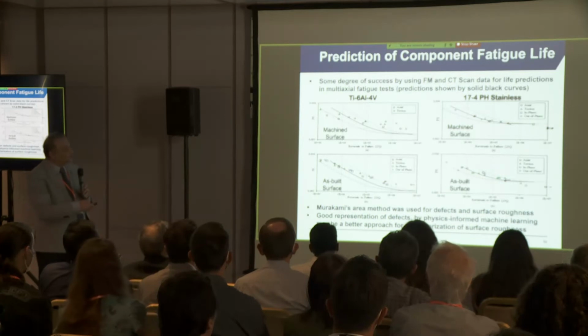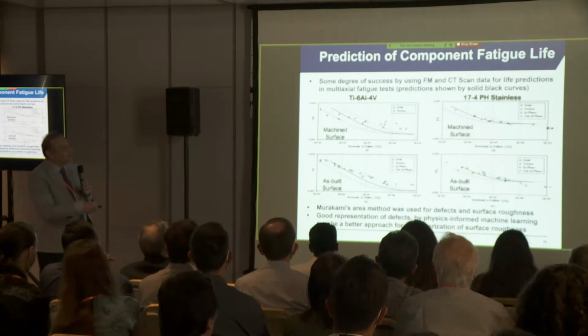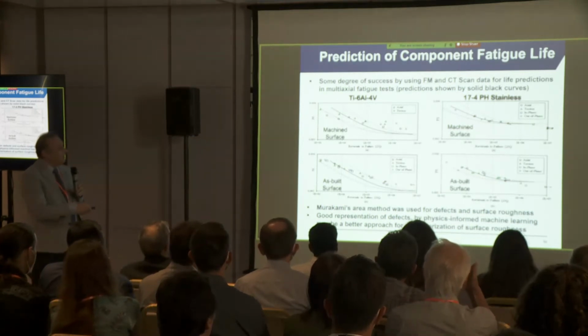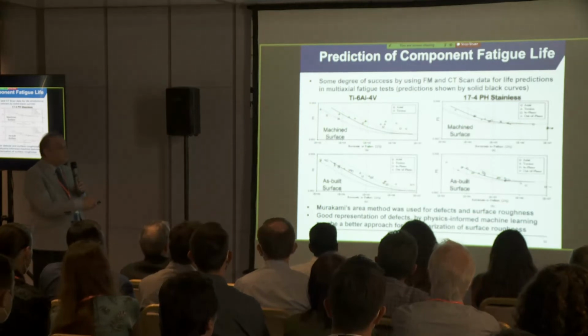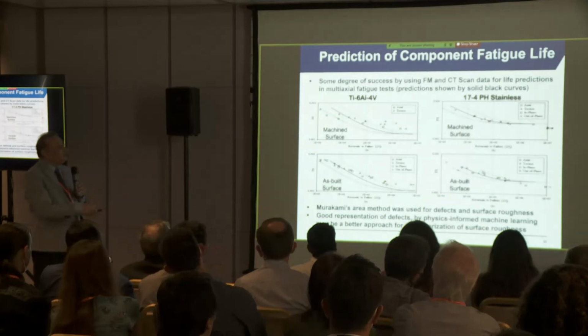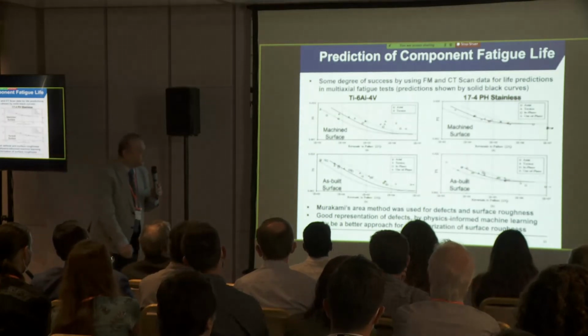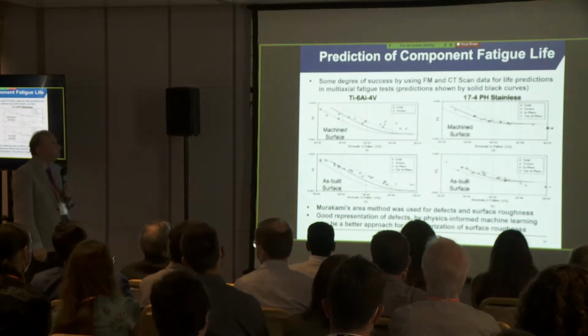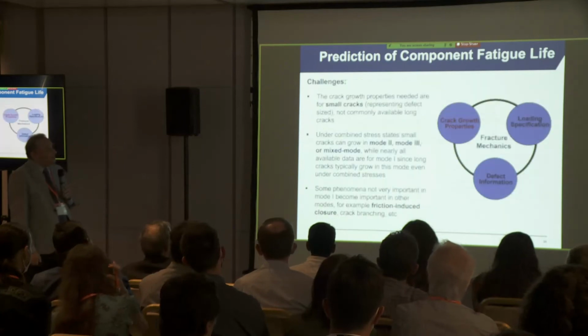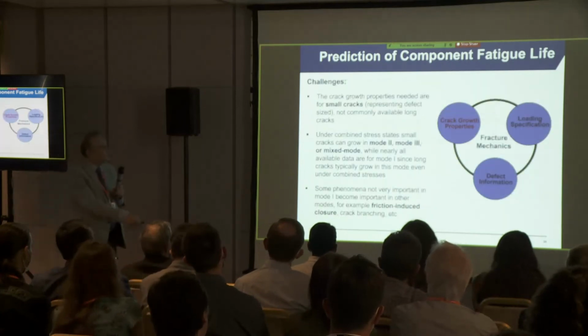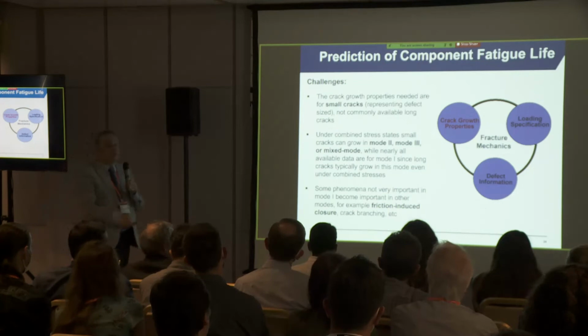The prediction from fracture mechanics is shown in the solid curves, and the data from different types of loading are shown. In some cases, you see relatively good approximations. In some cases, not so much. Okay? The challenge with using fracture mechanics is in terms of crack growth properties.